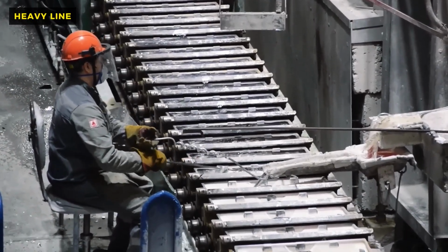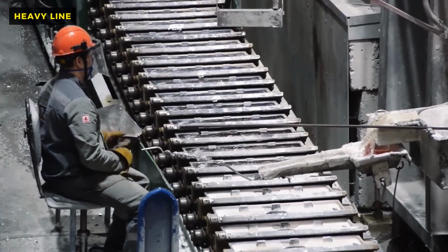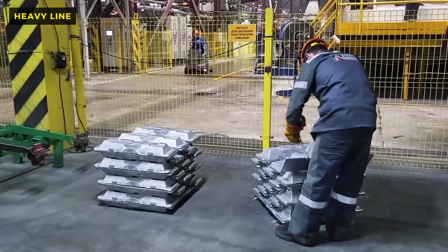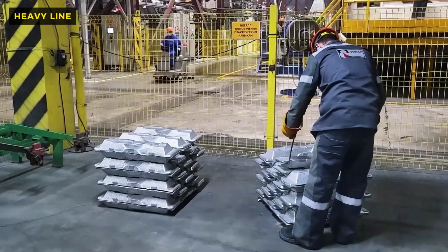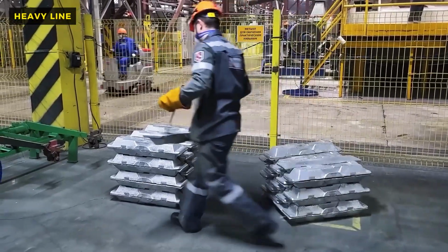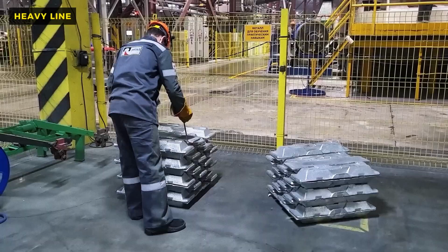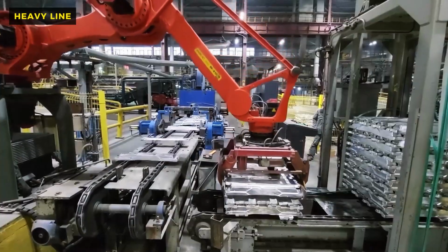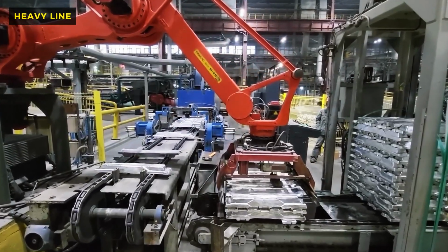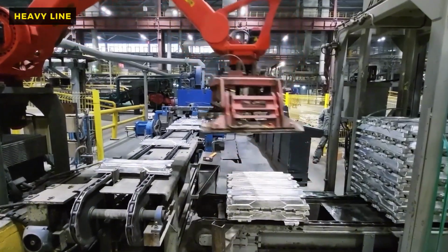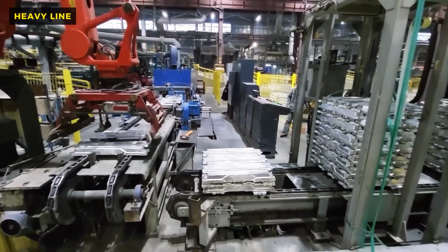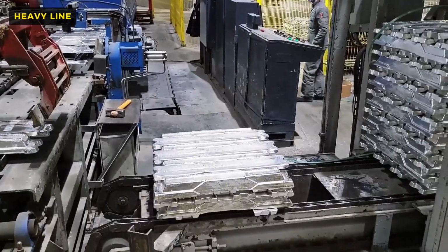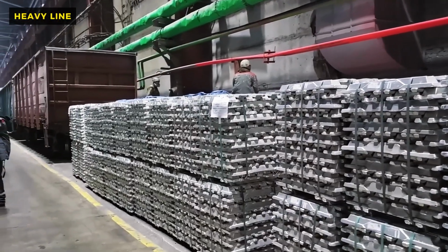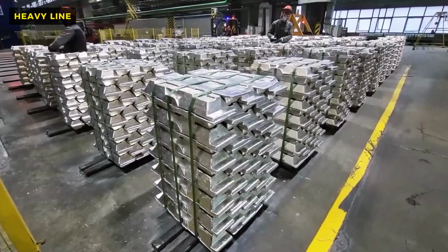The liquid aluminum is at 960 degrees Celsius, and it looks exactly like water, with no visible glow and bright light to warn of its temperature. If a single drop of water were to find its way into that crucible, perhaps from a leak in the roof or condensation on a cold tool, it would instantly flash into steam, expanding 1,600 times in volume and causing a steam explosion that sprays molten metal like shrapnel.